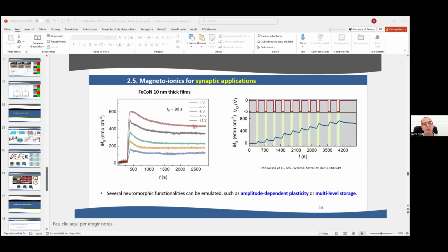There are a lot of works with oxygen in the literature, especially if you have very thin layers of cobalt, for example, in contact with gadolinium oxide, where the effect, instead of a full oxidation or reduction, is just adsorption at the interface, then it's much easier to reverse. So with oxygen you can do it, but provided that you don't fully oxidize or reduce. If you fully oxidize or reduce, then you have limitations because it's a full structural transition.